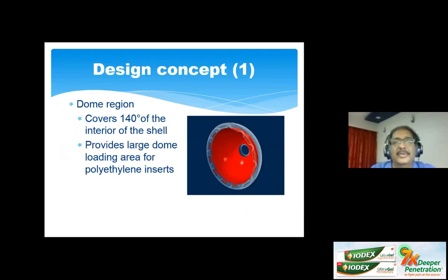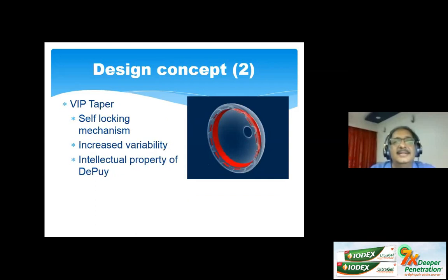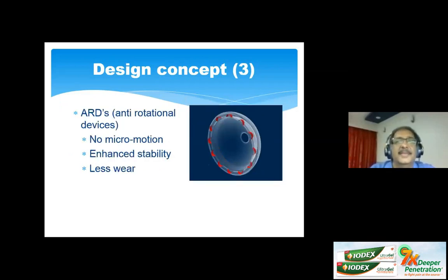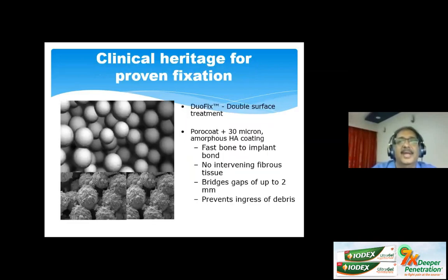It's a dome which was 140 degrees of the interior of the shell, and a big, large dome loading area for polyethylene inserts. It has a self-locking taper mechanism. It can increase the variability as to what type of liners you can use with this. And it has got some anti-rotational devices to have secure holding of the liner to improve stability and have less wear.